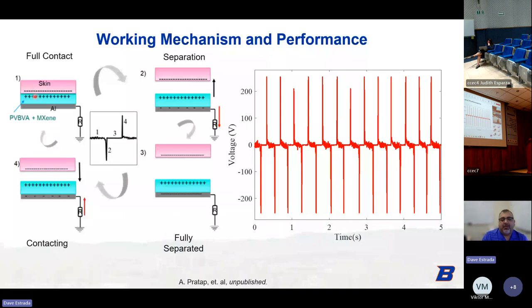Where you can kind of start with your TENG device. We're using a single electrode configuration. So we have our PVBVA+MXene film on aluminum, and then you can touch it just with your finger, right? And when you're in contact, that charge is equalized and you're kind of neutral, no charge is generated. As you begin to separate your finger from the device, you're gonna induce some charge redistribution, you'll generate a voltage, and then eventually at far enough distance, you'll be fully separated and you'll be back to charge neutrality.